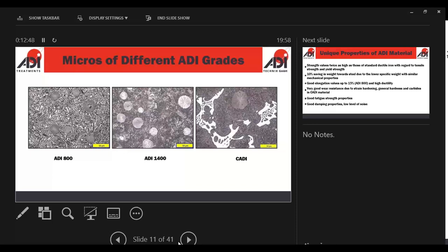In the middle, we see an ADI 1400. This is a high grade of ADI. In this structure, we have a very fine matrix of the ferrite needles. And those ferrite needles can actually contain some precipitated carbides in them, more like a bainite that you'd see in steels. And the austenite volume fraction drops off considerably, down from about 30% to 10% or even 5%.